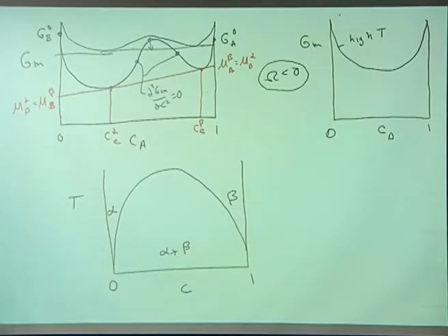The other thing that will become important, as we'll see, are these points here, where the second derivative of the free energy with respect to composition equals zero. Those are called the spinodal points.